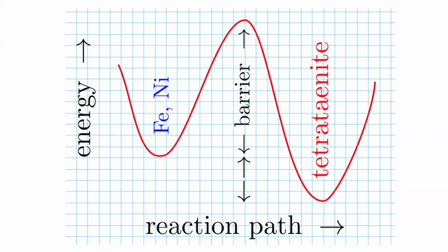And one idea which I would like somebody to try, and I don't have the facilities, is to make the disordered iron nickel compound solution in the glassy state. Because if you anneal the glassy state at a low temperature, it will reorder easily. So I need somebody to make this iron 50, nickel 50 solution in the glassy state. So we can get metallic glass, all right? But this would be difficult to cool sufficiently rapidly, but look, nothing in life is easy.